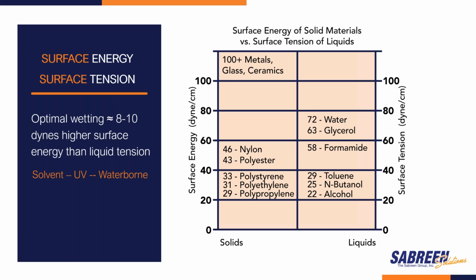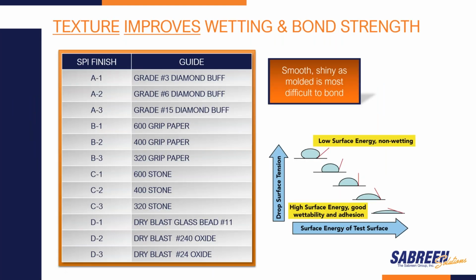Just real quickly, we want to note that the dyne is a unit of force, where 1 Newton is equal to 10 to the 5th dynes. But look carefully at this chart, because when you look at polystyrene at 33 dynes and compare that to nylon at 46 dynes, you may be thinking, oh, the surface energy of nylon at 46 is higher, so theoretically it should be easier to bond than polystyrene. Well, as we're going to talk about, the answer to that is no. But this is a general indication of where we want to be on surface energy relative to surface tension.